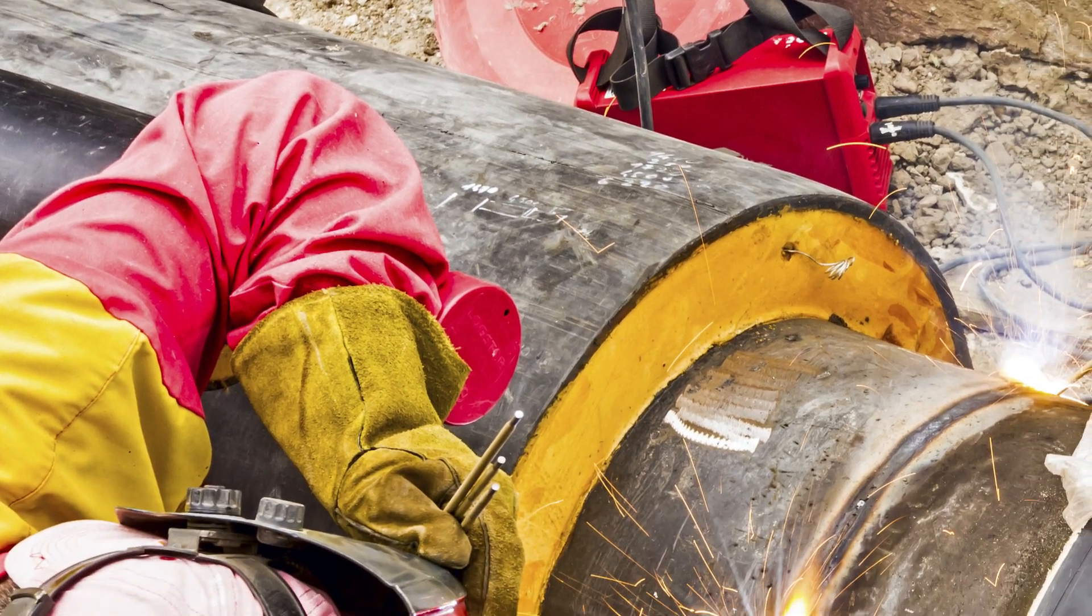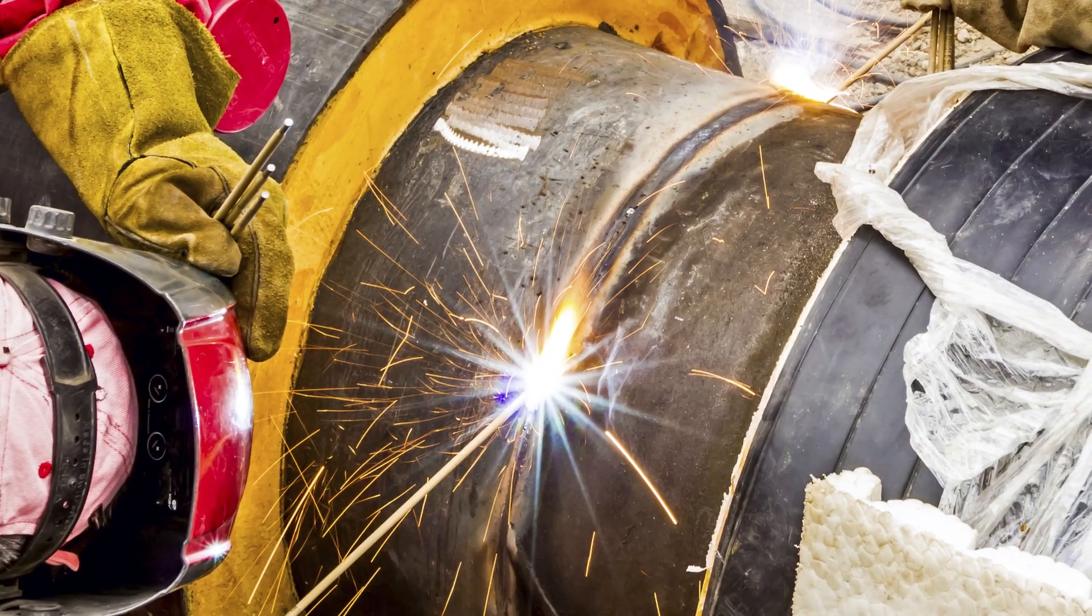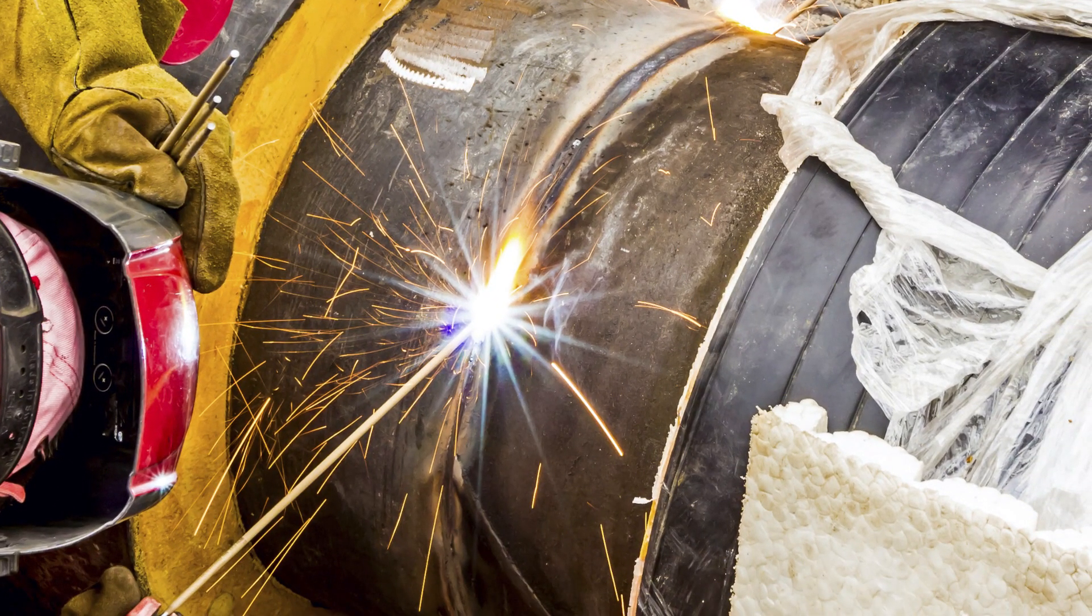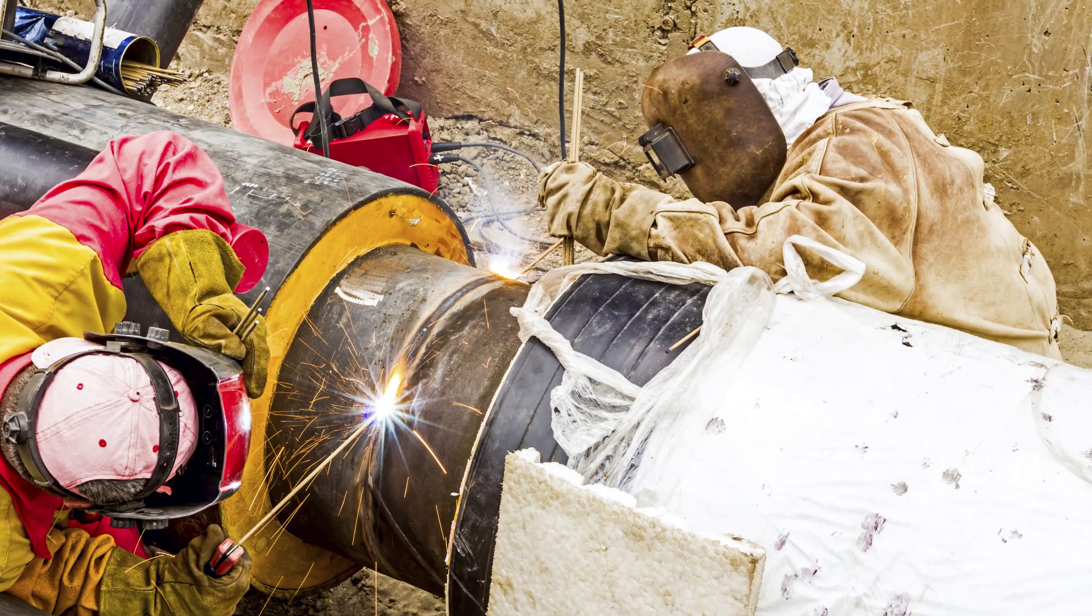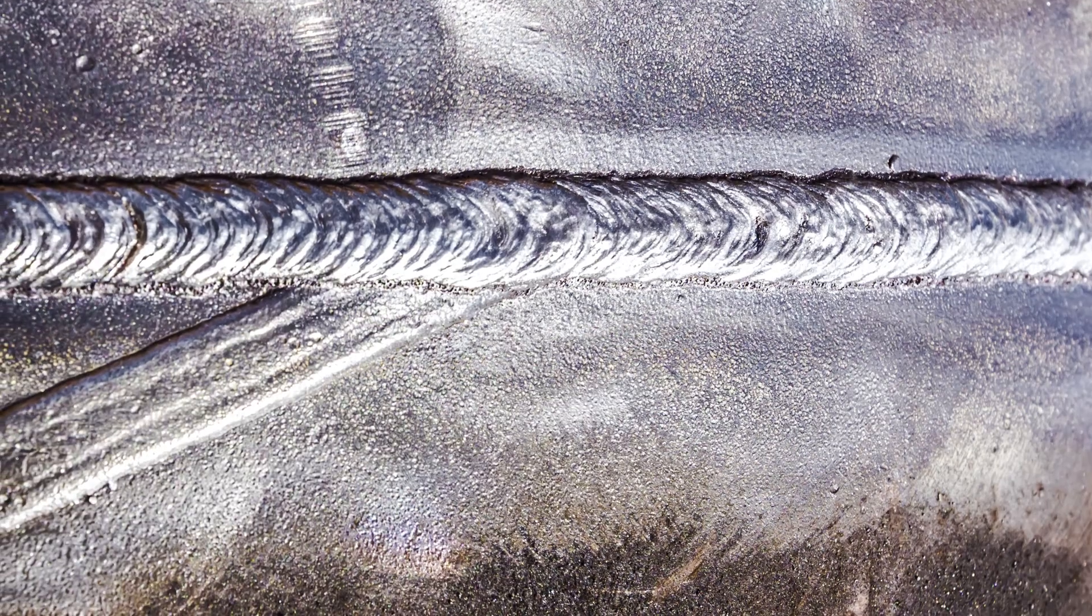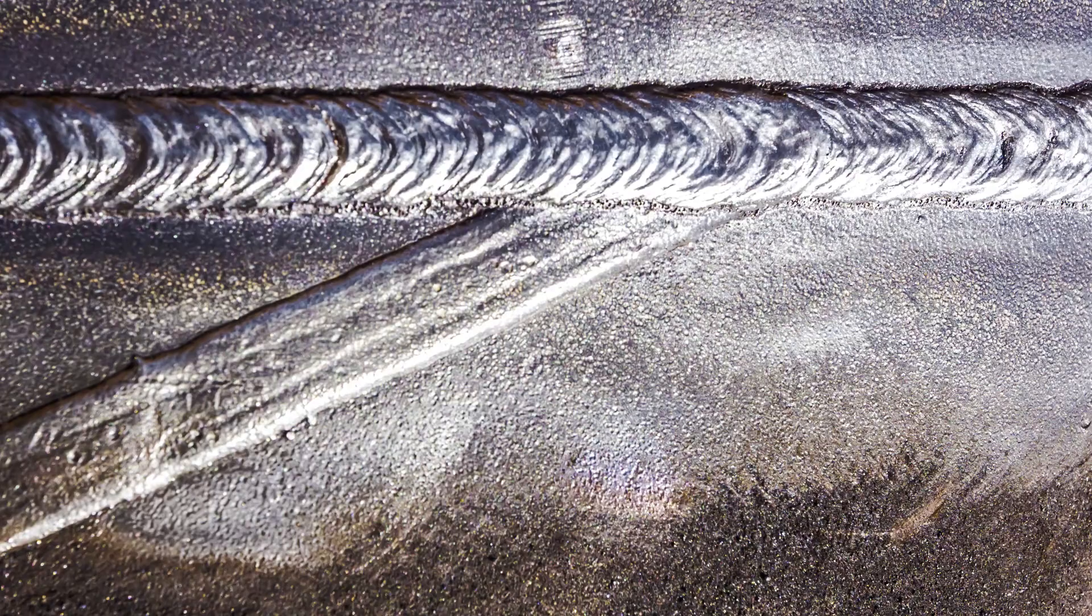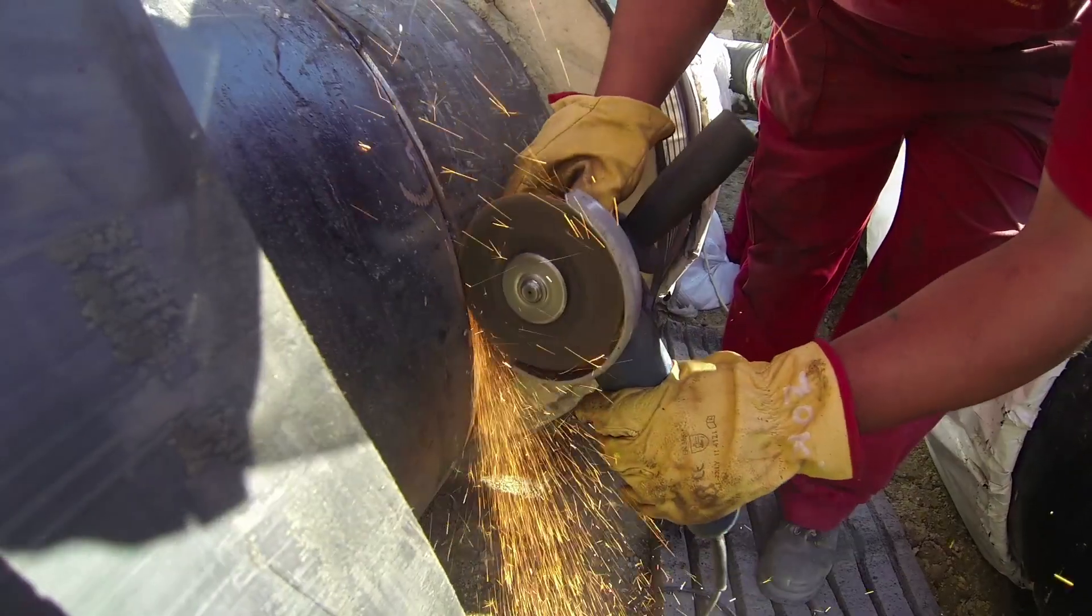In sour crude oil pipelines the risk of sulphide stress corrosion cracking is highest at welds due to the thermal and mechanical damage induced by the welding process. Recent work at NPL has investigated the effect of typical welding procedures on sulphide stress corrosion cracking of stainless steel pipeline materials.